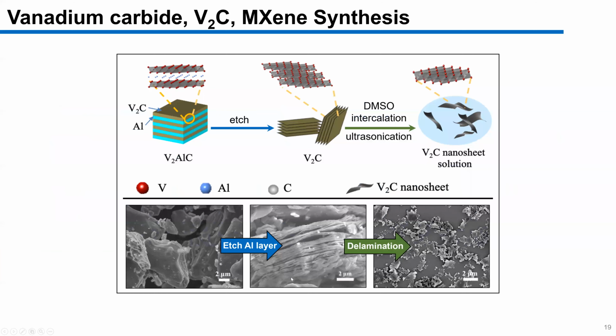Okay, so first what we did, of course, was make the MXene material that we are interested in. And as I suggested, we are interested in vanadium carbide. And here's a schematic of how this material is made. As I described, you have these vanadium carbides that are sandwiched between layers of aluminum. So here's what that looks like on the bottom left, an SEM image. If you apply hydrofluoric acid and you etch away the aluminum layer, then you are left with a multi-layer vanadium carbide material shown here. You can see clearly the layers that are formed after you remove the aluminum layer.